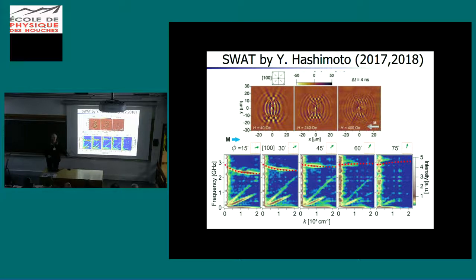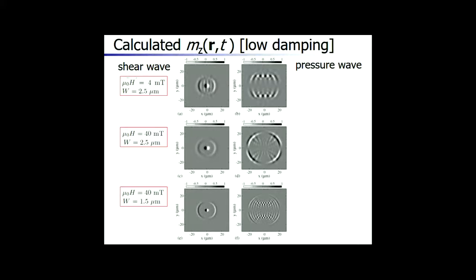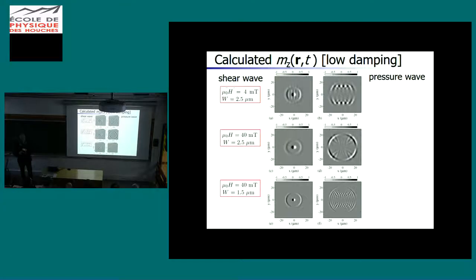So we tested now our method and see whether we can explain this as well, and this works actually quite nicely. Here we see now for a lower damping the excitations after 4 nanoseconds in this case, for shear waves, for pressure waves, for different spot sizes, because you need a focused beam in order to reach these crossing points, this magnon-polaron type of excitations, and magnetic field. If you have a large magnetic field, you can shift these crossings out of reach of the optical spectra. The spot here is 2.5 micrometers, which is a little bit broader. This one here is more focused.